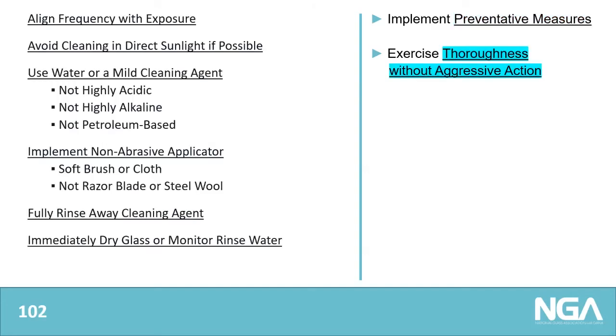In terms of the nature of cleaning, we want to be thorough without being excessively aggressive. We want to align the frequency with exposure. We don't want to risk scratching the glass by cleaning it too frequently, but we don't want to make the cleaning so infrequent that permanent corrosion could develop in the interim.